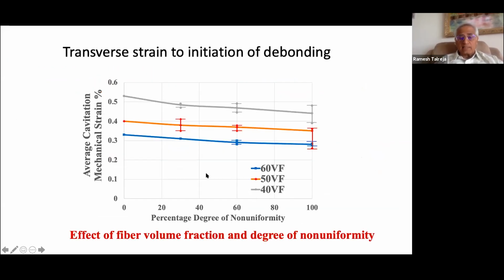Here's the final result, which I think is quite logical and understandable. What is done is to do this procedure of statistical RVE formation, virtual testing, and then do a number of virtual tests like you do in a laboratory and get a scatter. So these points are scatter points of virtual tests. And what is being plotted is the mechanical strain that you apply to the virtual specimen and find the first point of the loading that you have brittle cavitation occurring.